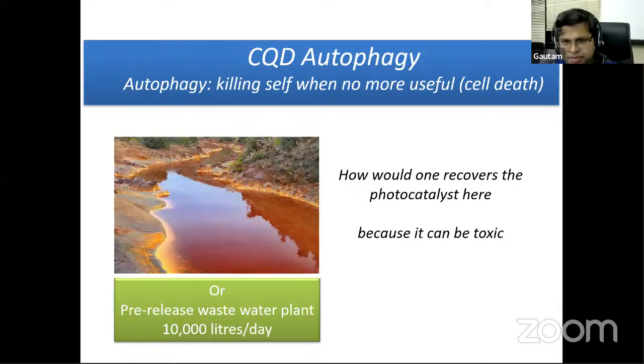I explained why this is important. If you want to clean natural water bodies, very hypothetically, you have these carbon dots, which are very cheap, you make them from waste plastic. The only thing you use is H2SO4, which can be recycled. So the plastic goes to carbon dots, and you throw some carbon dots in this river. Ideally, water will become clean. But the problem remains that you have to recover the catalyst. Otherwise, the catalyst itself will become a pollutant.